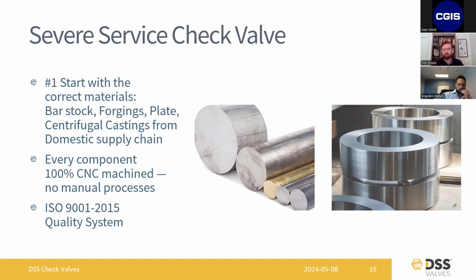So to prevent that and to prevent the need for additional impact testing of the material, it's easier just to use wrought material. It's well set up for our processes because every single component of our valves, whether it's the seat insert, the disc, the body, they're all CNC machined. So every single surface has a highly nice surface finish on a CNC mill or lathe. And as expected, our whole shop, our entire company is ISO 9001 certified. So we maintain traceability from the steel mill where the material is produced all the way through the end product.